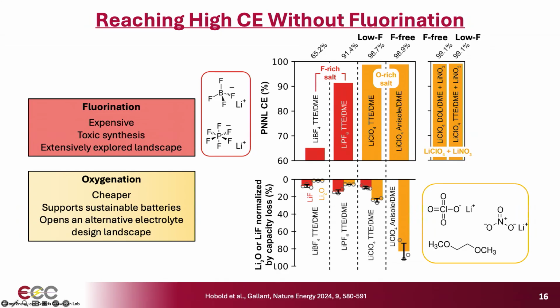And I would argue that we've already extensively explored the landscape, not exhaustively, but it would be nice to open up new directions in electrolyte design. So we did that, and we set about developing electrolytes that rely on fully oxygenated anions instead of oxygenated fluorinated or fully fluorinated ones. Some oxygen-rich additives such as nitrate shown here, and then all based on an oxygenated solvent, DME, shown here. And so we designed both low fluorine and fluorine-free formulations using these.